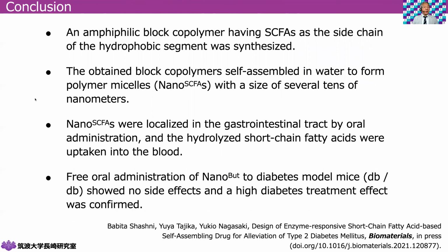In conclusion, an amphiphilic block copolymer having short chain fatty acid as a side chain of the hydrophobic segment was synthesized. The obtained block polymer forms nanoparticles of several 10 nanometers.